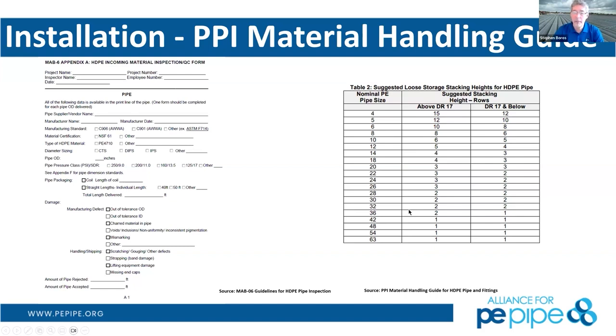Stacking heights as well. Polyethylene pipe you can stack. The larger diameters, though, it's recommended that you don't stack more than one high. Once you get below 36 inch, you can stack it 2, 3, 4, even 10 high, as long as it's chocked properly and protected properly, or it's not going to fall off and roll over people.